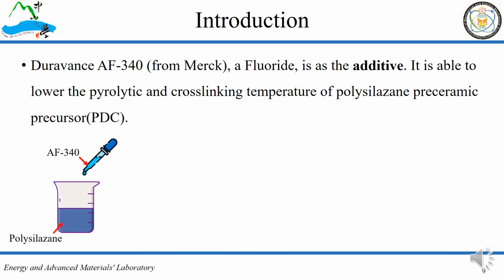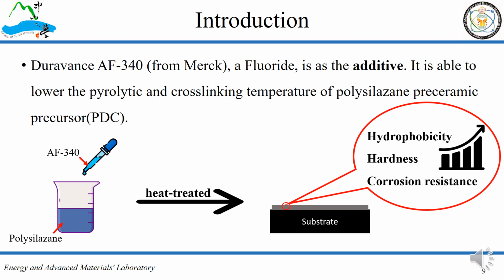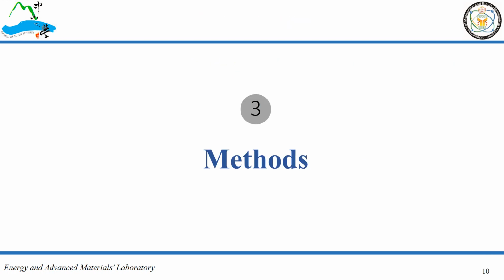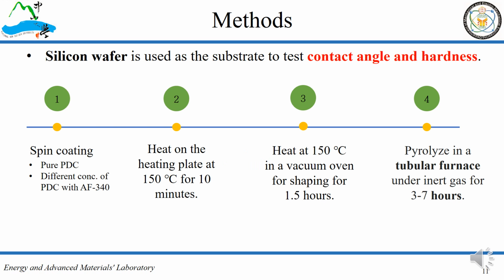AF340 is one kind of fluoride. It is able to lower the pyrolytic and cross-linking temperature of the polysilazane. By adding this additive, the hydrophobicity, hardness, and corrosion resistance of the coating layer can be improved. Silicon wafer is used as a substrate to test contact angle and hardness.